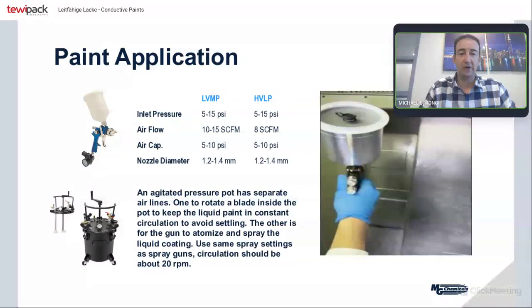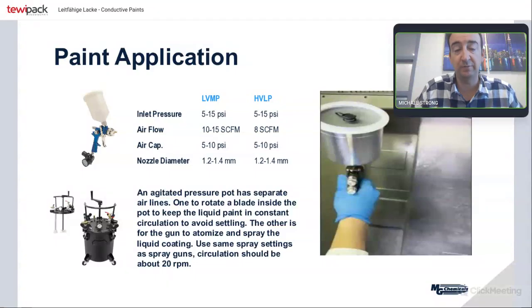The other is the spray pressure. If you go too high, you tend to separate out the two components of the paint, the binder and the conductive filler, and it does lead to poor results. And I've actually done customer site visits where the root cause of their issue is simply they use too much pressure. We prefer low pressure, and that gives you good wetting, but it also ensures your film is homogeneous.